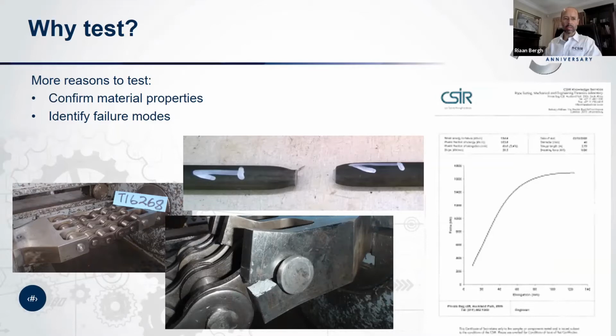And lo and behold, when we had everything set up and we did the ultimate strength test, as you can see in the photograph there in the bottom middle, it wasn't the chain that failed, but the test fixture. So plans had to be made and extra work done. Not a pleasant experience. And what we learned from this was the bursting open or the fracture of the clevis tongs at the end in front of the pin was a failure mode that wasn't anticipated. And had we been doing tests on items of this nature and having seen destructive tests where a similar clevis type was tested to destruction, we would have anticipated that failure mode as well.